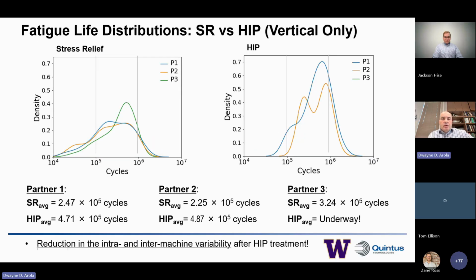If we break this down now into individual partner contributions, but now just focus on the vertical orientation response, you can see that in the stress relief condition, we see a relatively broad distribution, I should say, of the actual fatigue lives. And then what we see on the right is, at least from what we've been able to develop so far, the distributions agree quite well. You see a narrowing overall in the fatigue lifespan. So we get a reduction in the intra-build variability. And then what we're seeing so far in comparing results of the partners P1 and P2, and P3 is almost finished, that we're also getting a reduction in the degree of inter-machine variability as well after HIP treatment. So we're very happy to see that.